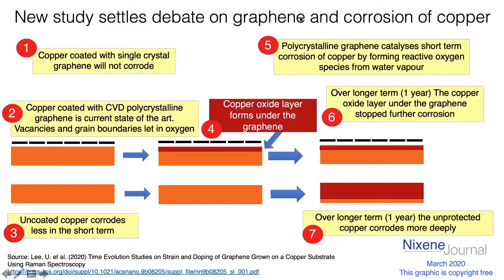Yes, exactly. And the important point, I'll stop sharing now, we can get back to seeing one another. So the important point is that we just need to be aware that the graphene that's grown on copper foil at the moment by the CVD process is polycrystalline. Very few people will tell the average person that, so you don't realize that's what's going on. And these little gaps and cracks are what let the oxygen through. But when we eventually get to make single crystal graphene, then that will be a perfect barrier, and we'll get perfect protection.